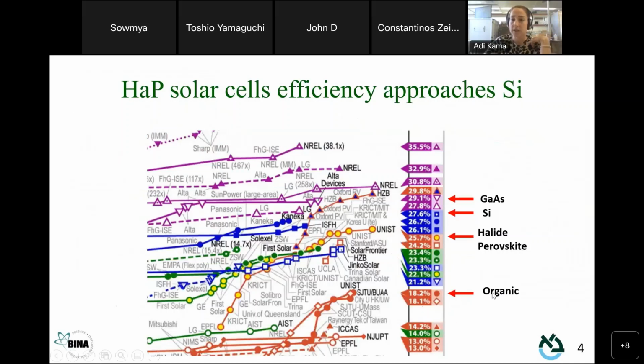So we have the organic solar cells that are already achieving 18% efficiency. We have the halide perovskite very close to silicon with 25% efficiency. Silicon's best cell has 27% efficiency. We also have gallium arsenide with 29%, which is used only in space. And we have a new type of solar cells, the tandem solar cells, which are multi-junction solar cells usually used with silicon and halide perovskite. I'll show a bit more about it in a minute. It has a very recent new record of 30.9%, and it's improving very fast in the last few years.